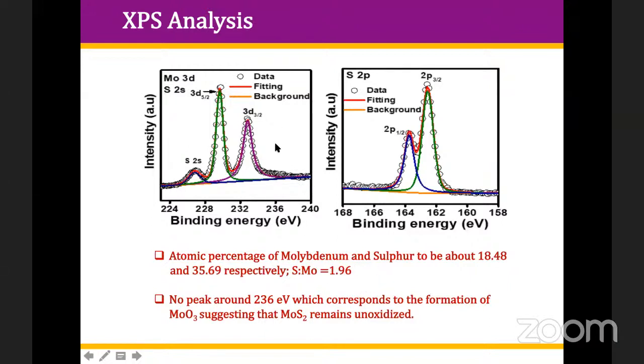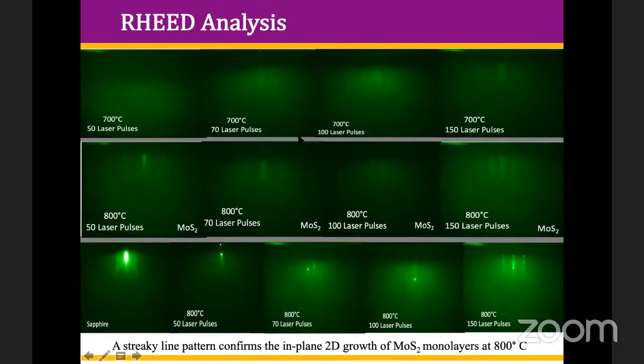And further, there is no peak at around 236 electron volt, which represents the formation of oxide of molybdenum. This clearly indicates that there is no trace of oxygen in the XPS in the growth of MoS2, and pure MoS2 has been obtained by using the pulsed laser deposition technique. So these are some RHEED analyses.